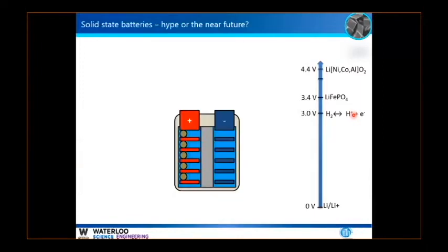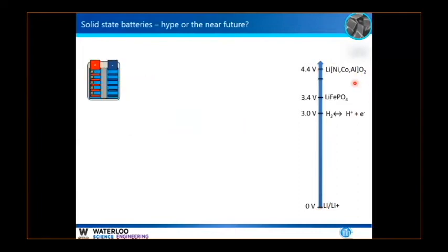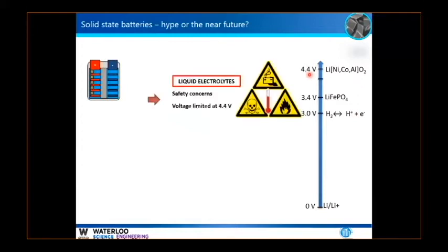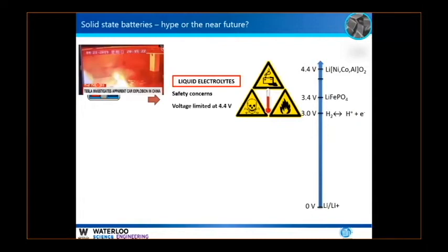So we go back to our battery with our positive and our negative electrodes, and we look at an energy. This is a voltage scale of lithium versus a typical positive electrode material. As I said, this is at very high voltage. The problem with these electrolytes, as I mentioned, is that, first of all, their voltage is limited here because they decompose beyond that, but they decompose in a way that produces very resistive layers on the surface of this positive electrode. And this causes fires.